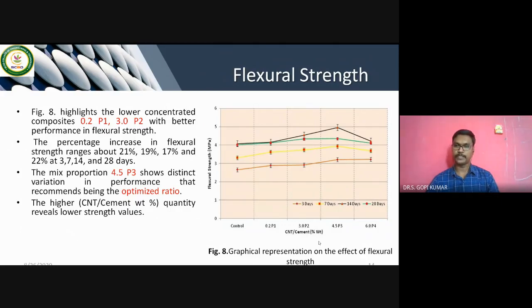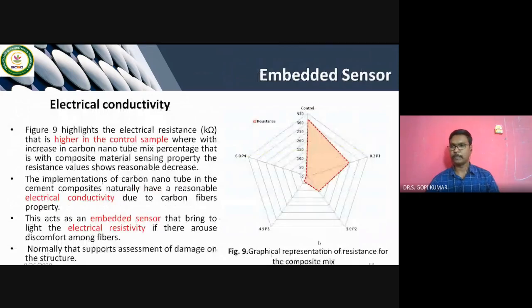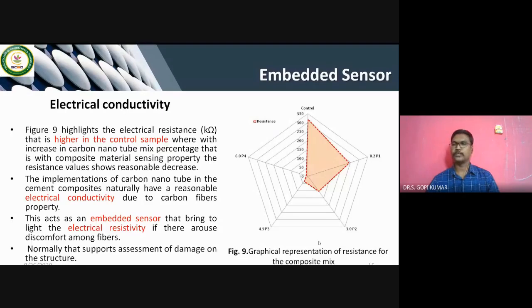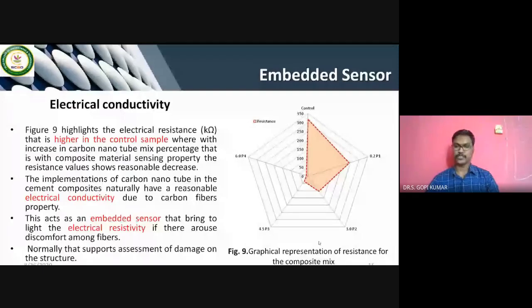And now, embedded sensor, where the resistivity is evaluated considering the sensing property. Initially in control the resistance is higher, where with subsequent weight percentage the resistivity shows a little lesser value, but the electrical conductivity due to carbon fiber, the carbon nanotube, is predominant. This acts as an embedded sensor when there is need, when electrical resistivity is applied. And normally this parameter supports assessment of damage on building structure.